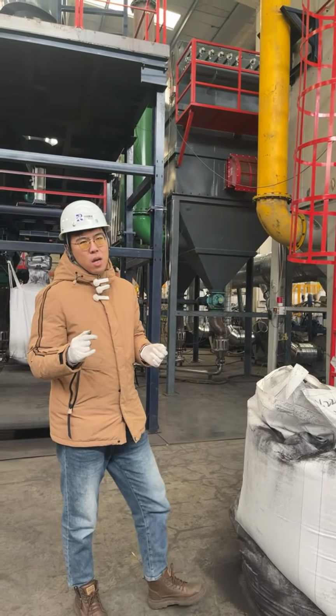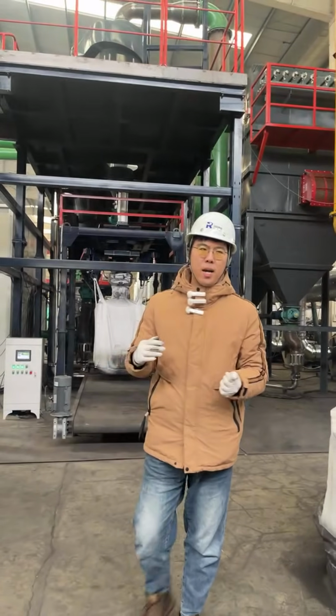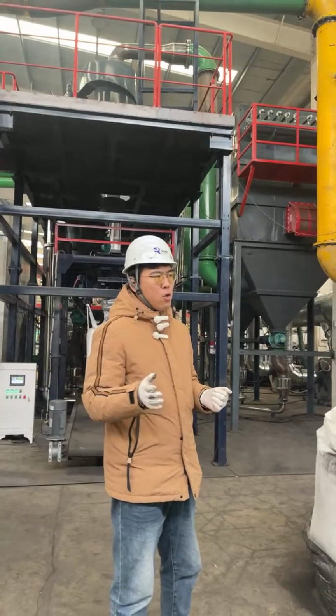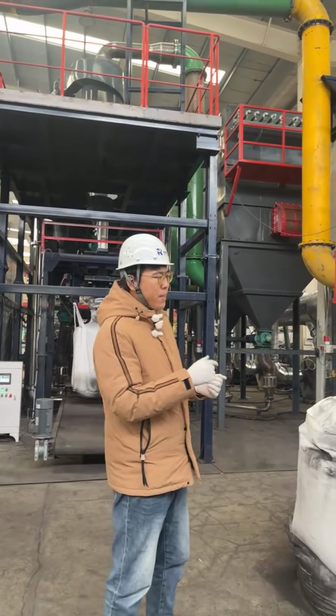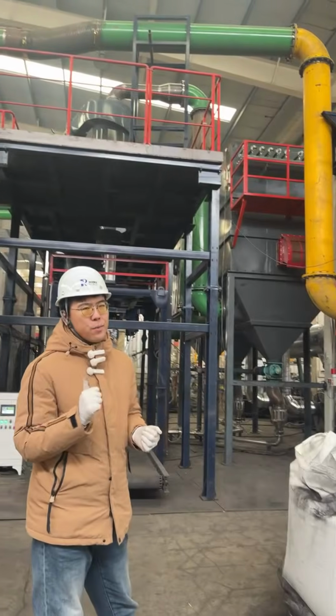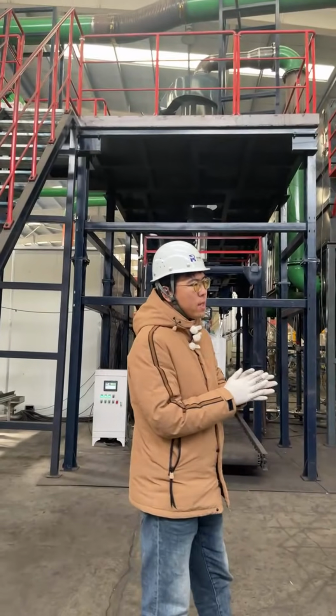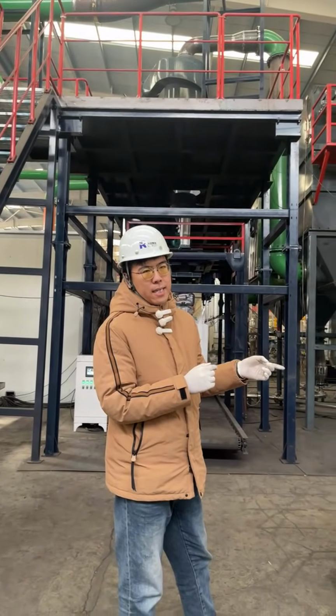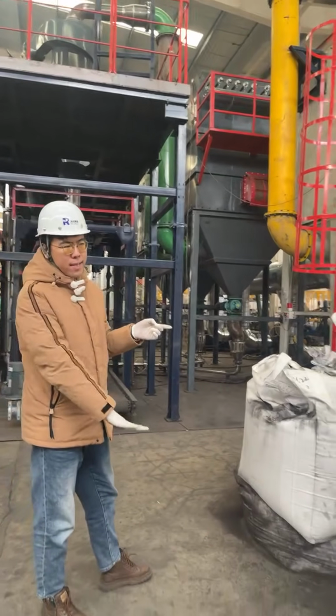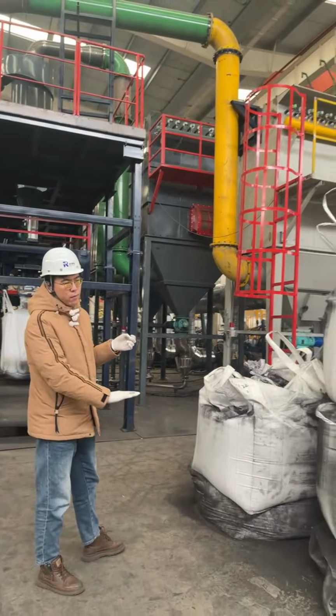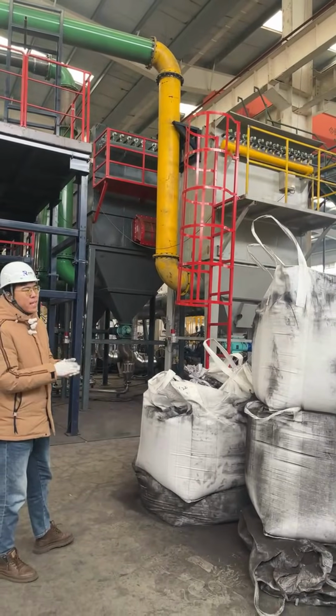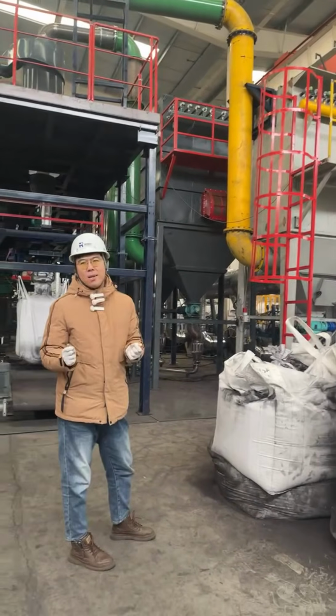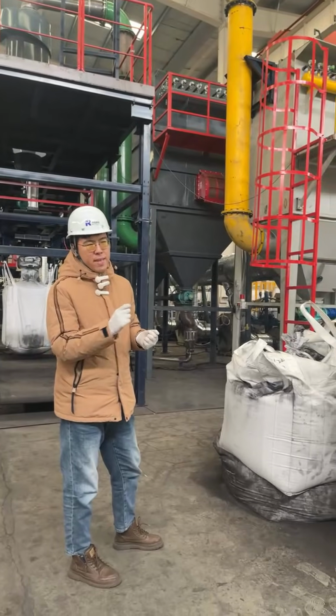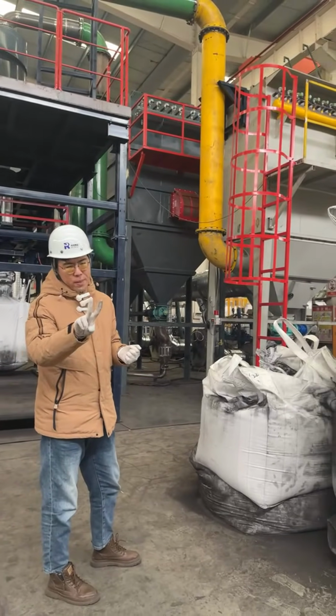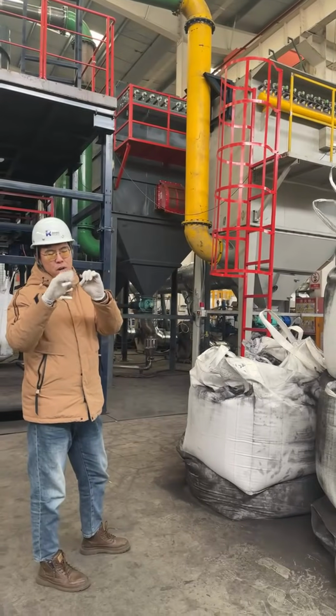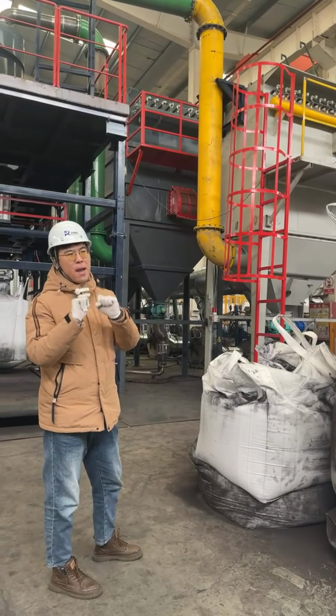It will need cost about 2 million US dollar per year to remove the aluminum. And inside our black mass, because we are using a very unique system, the aluminum content in the black mass will be lower than 0.5%. But in other processes, in many other plants, the aluminum content is usually higher than 2%. But here we will make sure it is less than 0.5%.